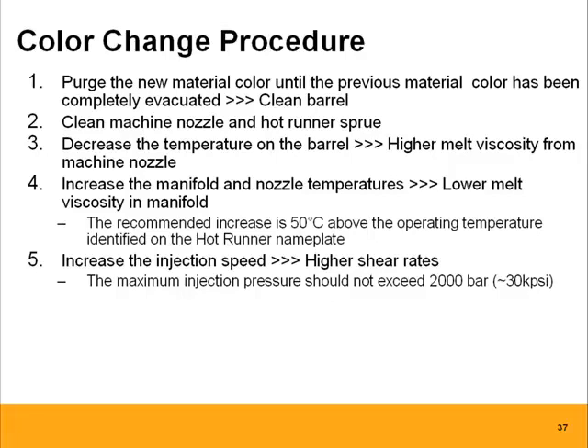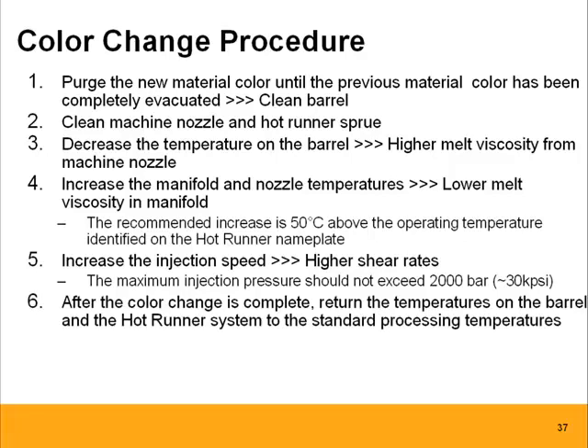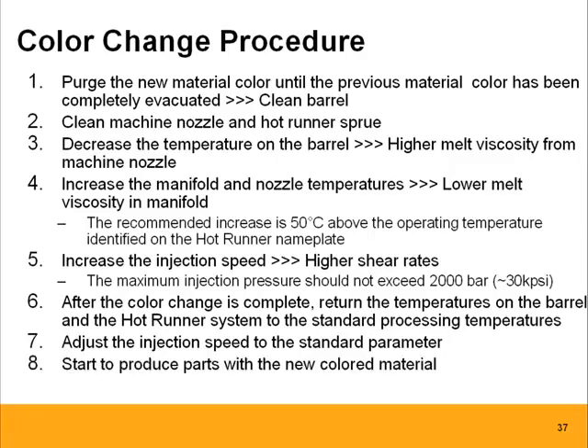After the color change is complete, return the temperatures on the barrel and the hot runner system to your standard processing temperatures. Of course, don't forget to adjust the injection speed to your standard parameters so you make the same quality parts as before. And then start to produce parts with the new colored material.